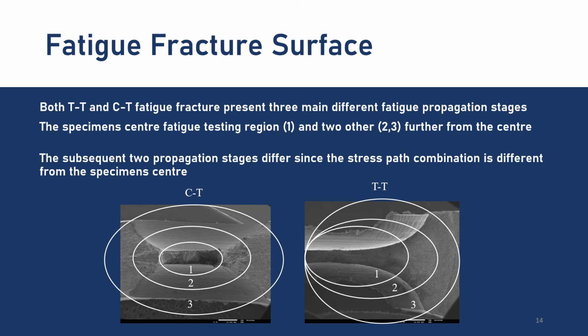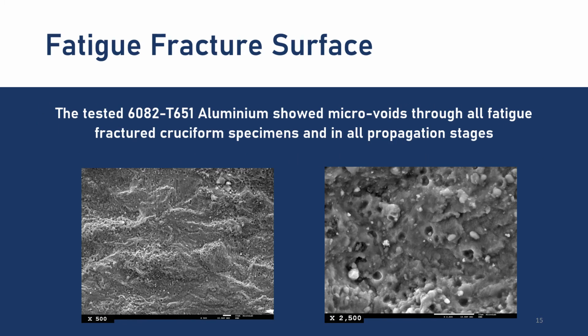The second and the third stage present a much higher propagation rate and changes in fatigue fracture morphology associated with changes of stress applying damage to the specimen. Also, by a general view of the fatigue fracture, we can see in all cruciforms, in all stages of propagation, microvoids present in the aluminium tested.